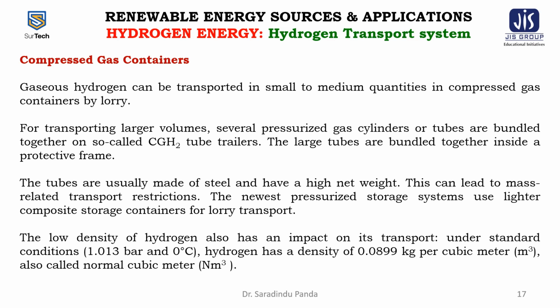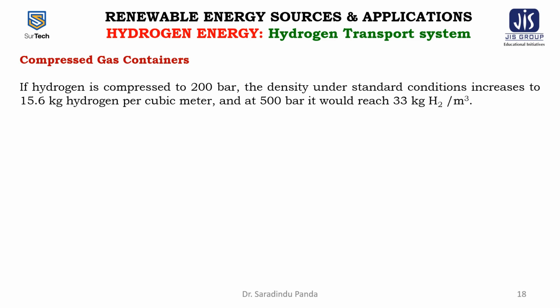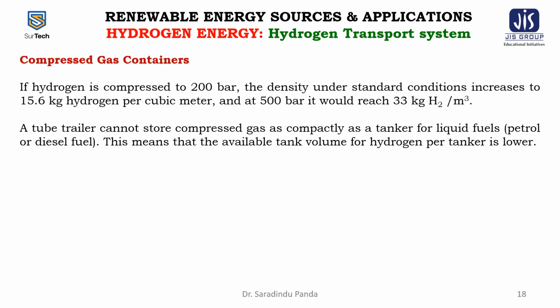The low density of hydrogen also has an impact on its transport. Under standard conditions, 1.013 bar and 0 degrees centigrade, hydrogen has a density of 0.0899 kg per cubic meter, also called the normal cubic meter, Nm3. If hydrogen is compressed to 200 bar, the density increases to 15.6 kg hydrogen per cubic meter, and at 500 bar it would reach 33 kg hydrogen per cubic meter. A tube trailer cannot store compressed gas as compactly as a tanker for liquid fuels. This means that the available tank volume for hydrogen per tanker is very low.